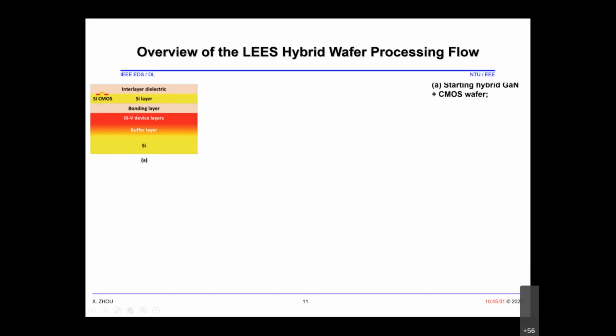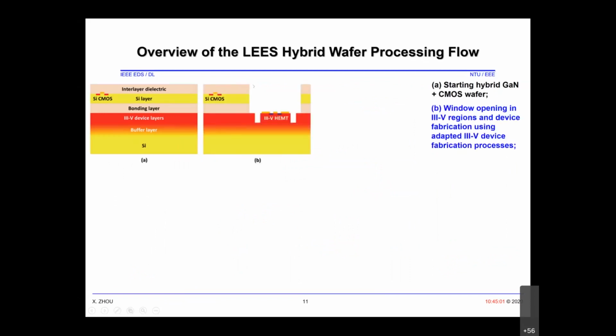Here's a brief overview of the hybrid device fabrication. So this is the CMOS device already embedded in the silicon layer with the dielectric on top, and then the III-V wafer already bonded at the bottom of the wafer. Then we dig the window where the III-V devices will be fabricated on the same wafer. Then we fabricate the III-V device.